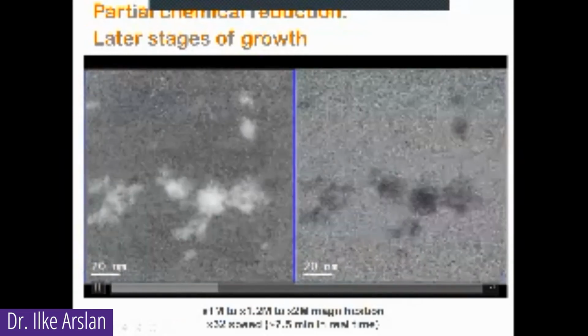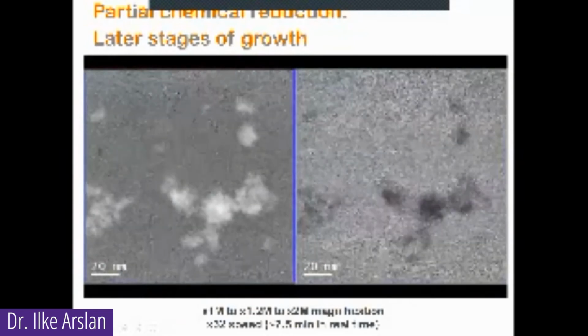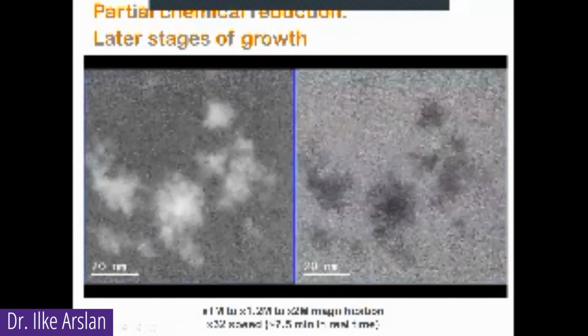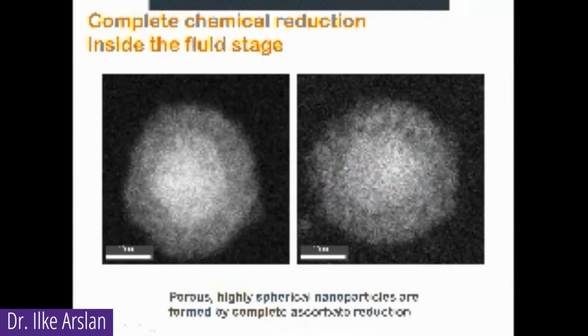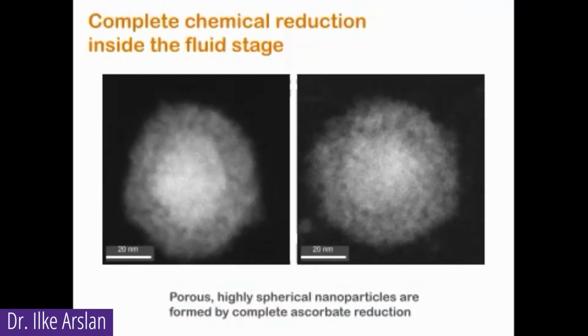That is what we see. And this is very similar to the particles that we looked at that were grown ex situ in the laboratory using tomography. So we know what the method is now based on this surfactant of how to grow these particles. And we did work to change that so that we could have aligned pores, so that the pores wouldn't interact with one another and then would become more stable.